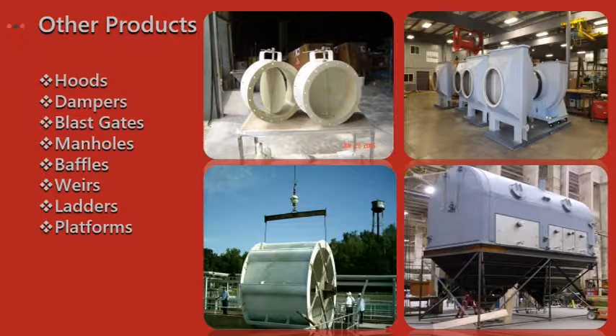The photo to the upper right is of some mist eliminator systems that we manufactured and shipped to Texas. The lower right is of a fiberglass plenum that we built for Lubrizol in Louisville, Kentucky. We've done a couple of these systems for them in Kentucky. Also sent one to Holland, and we've done various sizes of these for them through the years. But it's essentially a CPVC powder operation, and 316 stainless was being used in the plenums prior to the fiberglass, and the 316 stainless was being attacked and corroding. These systems have been in place for close to 30 years, and they still operate the same as they did day one.